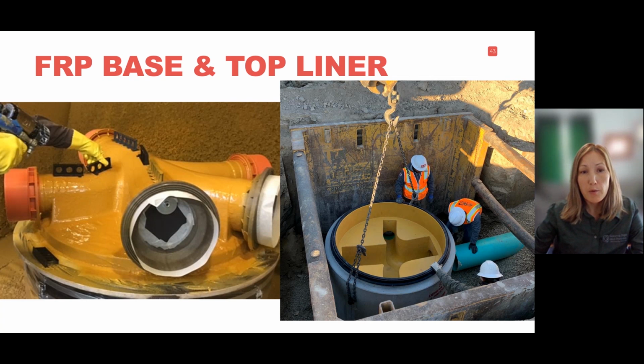Over here, you see how we make the liner. So basically, we make a negative mold of the channel, and then spray it with fiber reinforced polymer or plastic, and then we attach these black little parts called bonding bridges. We attach them to the liner, and then they're going to be cast and hold that liner embedded into concrete. It also has built-in connectors for different types of pipe. So if you have specific pipe, let's say SDR35 or DIP, we have specific connectors that can fit that pipe. In the photo on the right, it's one of our first projects, which was made in Utah.